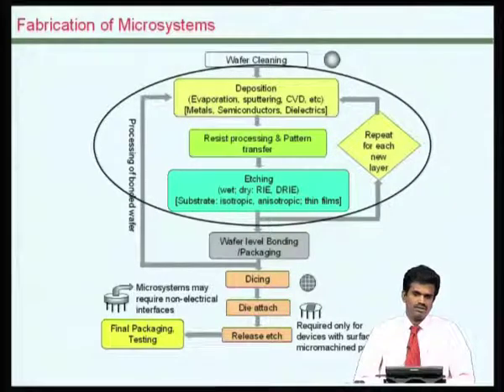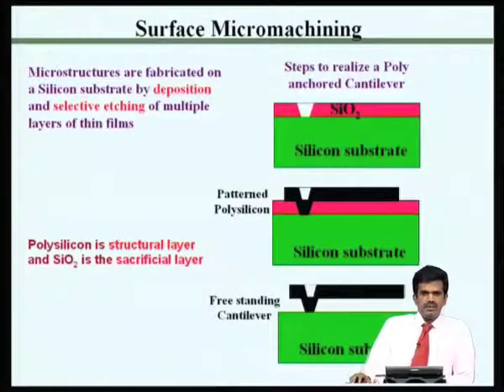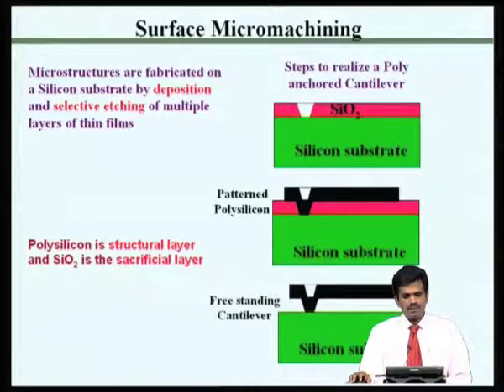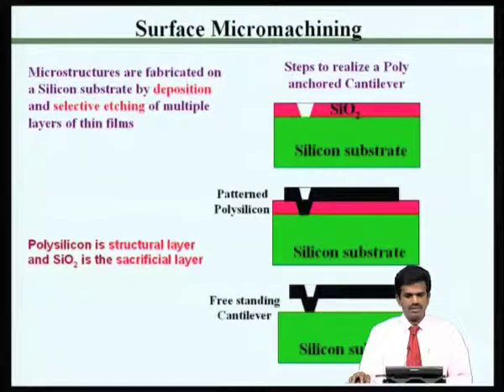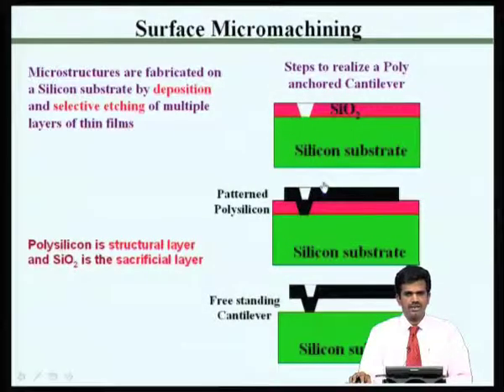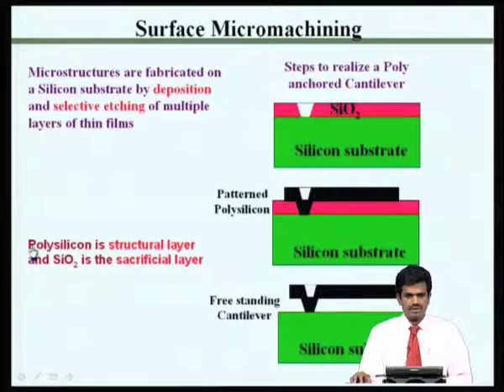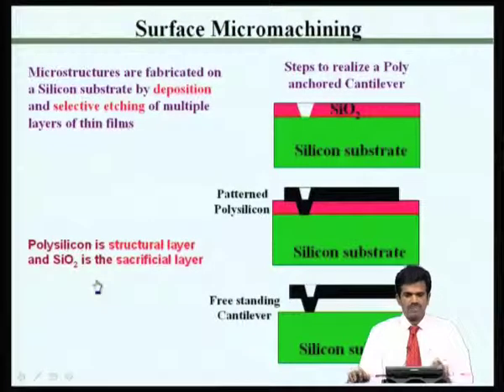Then you can add another film and continue this process. We have seen how this could be extended towards building free-standing cantilever structures like the one you see here. What we do there is to start with a silicon wafer, add a silicon dioxide layer which works essentially as a sacrificial layer, and on top of that add a polysilicon layer which remains as the structural member. These materials are tentative — you could use various other materials with some constraints in terms of their chemical and other properties.